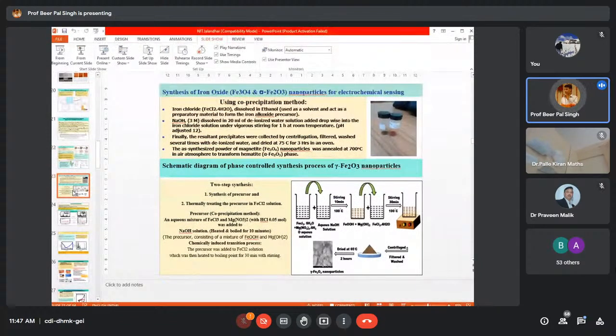In our research, we synthesized Fe3O4 iron oxide nanoparticles and the alpha phase of Fe2O3 nanoparticles. We synthesized Fe3O4 and alpha Fe2O3 by using the co-precipitation method and by a single method. In that case, at higher temperature, at about 700 degrees centigrade, Fe3O4, when annealed in open atmosphere, transformed to the alpha phase of iron oxide, that is hematite, alpha Fe2O3 phase.